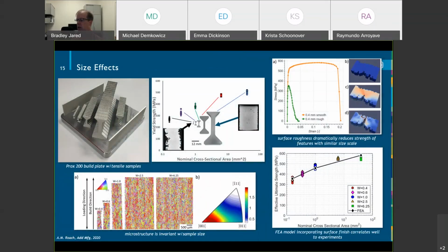One of the things that's really interesting in this space is the fact that these parts have a lot of surface roughness on them, and so you can actually get size effective properties, right? So people want to talk about material properties and additive components, and the reality is it gets really complicated sometimes. And so what happens is we think about sort of structural properties, right? So you have to really understand the dog bones. So this is some work we did and published, where we printed dog bones that went from, I believe, 400 microns in diameter, which is the small one on the left here, all the way up to 6.25 millimeters in cross section.